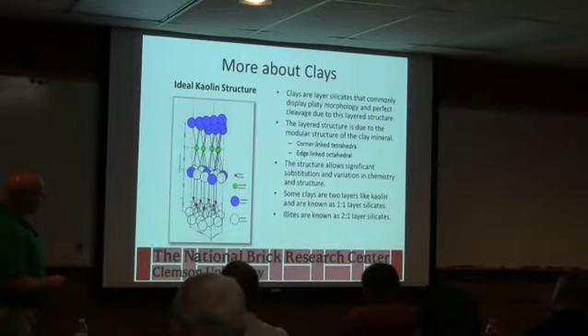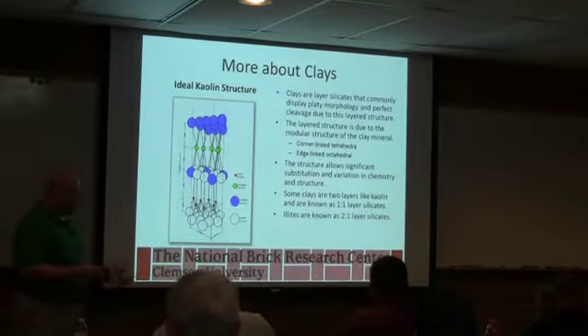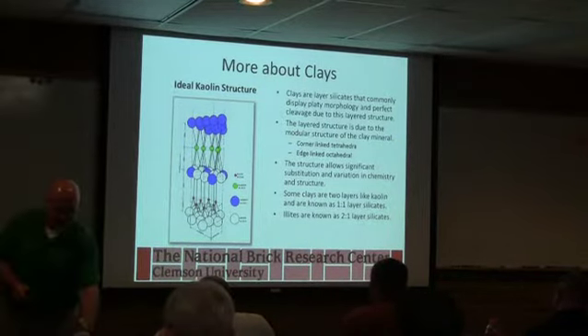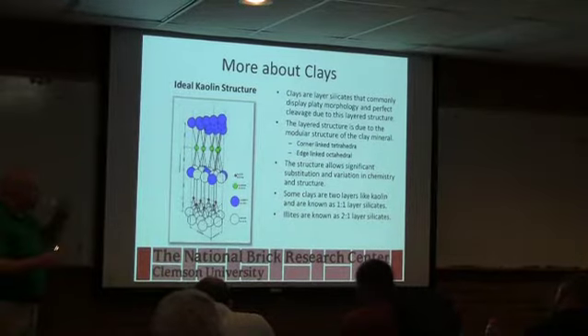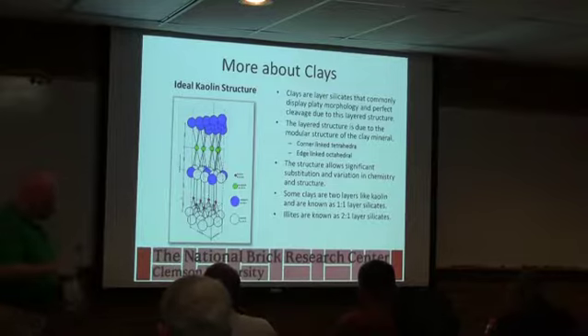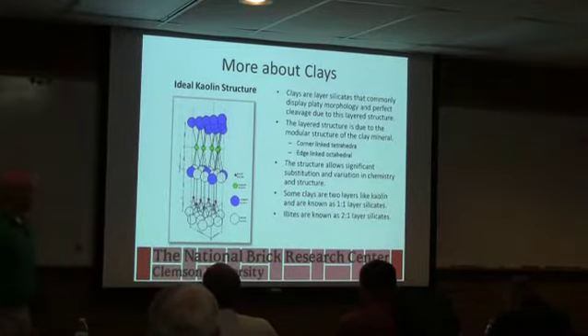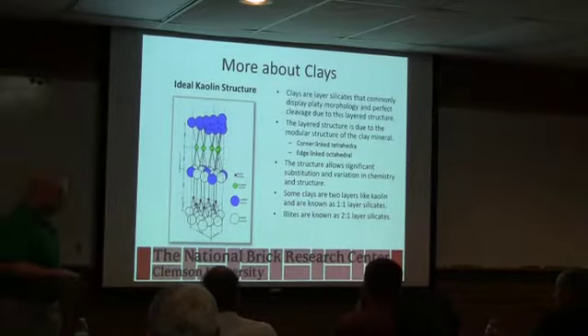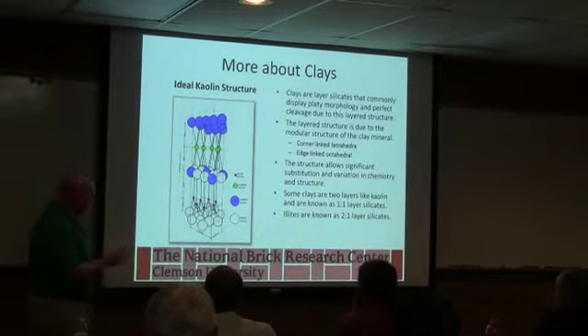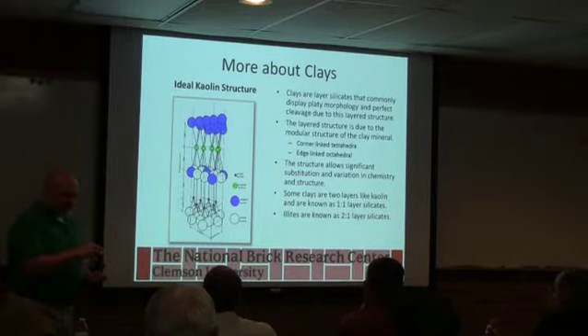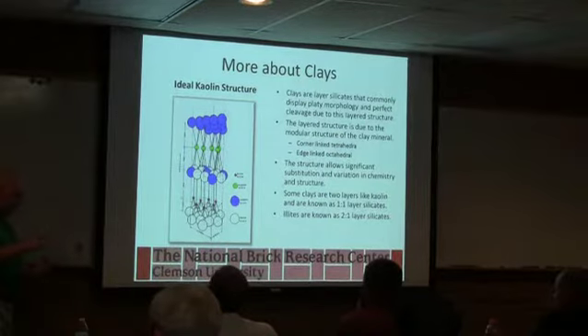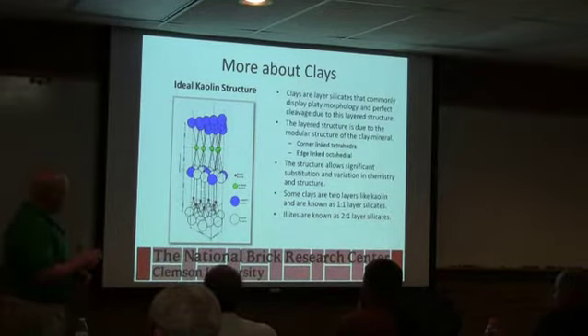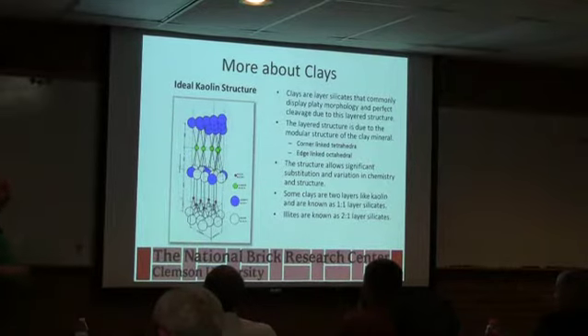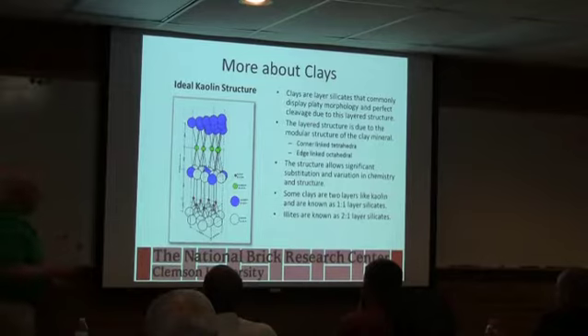I'm not going to bore you with this, but there are 4 types of clay minerals. Kaolin is sort of the main one we consider because it's in most materials. If you tried to look at what that crystal structure looked like, it would look something like this. Basically you've got these blue things, hydroxyls, and when that clay mineral decomposes in the preheat, you're losing that part of the mineral, and it's no longer clay after you heat it through that point. You have a relic until you start to get up to the point where you form glass. So if you heated something to, say, 1,000 degrees Fahrenheit, cooled it off and tried to re-extrude it, it wouldn't be plastic anymore, because you've destroyed this mineral that's giving you the plasticity.